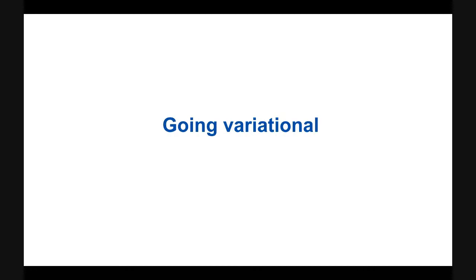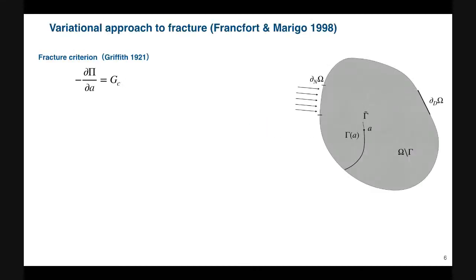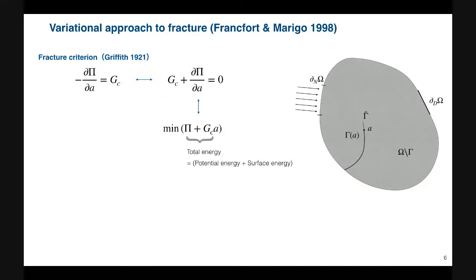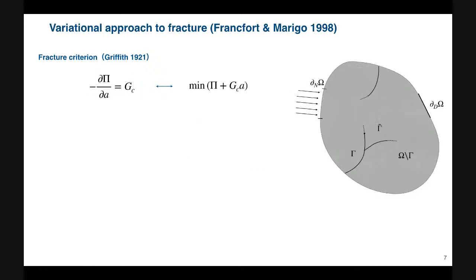Now, we look at fracture propagation from a different point of view. This was the Griffith criteria: when the energy release rate reaches some critical value, fracture propagates. Francfort and Marigo proposed a variational approach to fracture in 1998. The Griffith criteria essentially tells us to find the minimum point. If we define the total energy as the sum of the potential energy and surface energy, the minimum energy with respect to crack length A is identical to the Griffith criteria. So Francfort and Marigo recast the Griffith criteria into an energy minimization problem. But this criteria still deals with a single crack propagation. And what if we have multiple cracks or a crack branches?